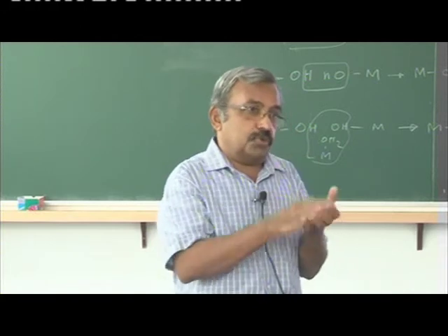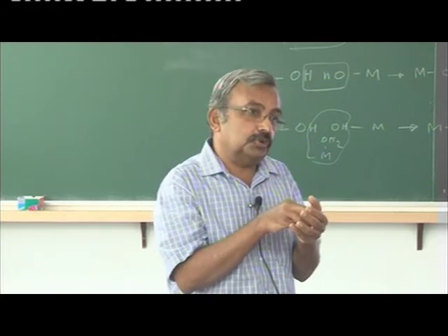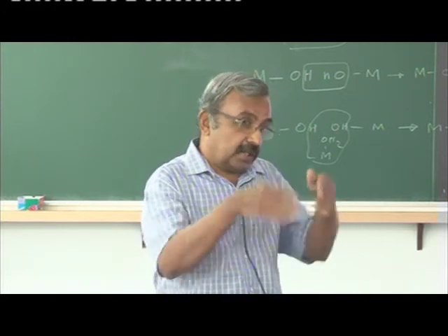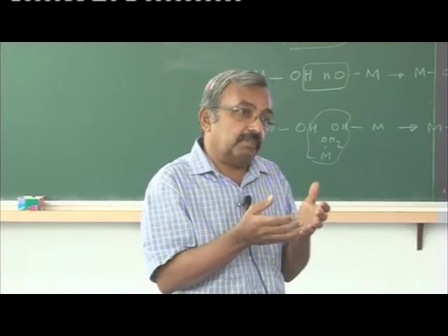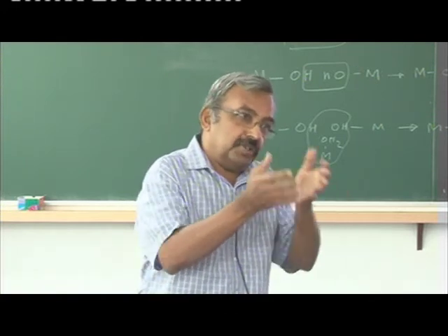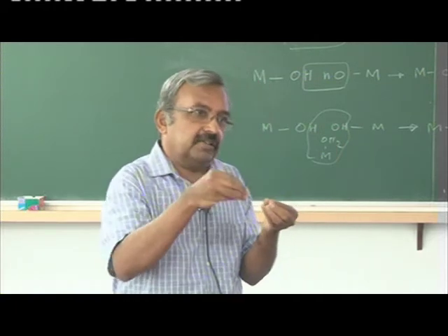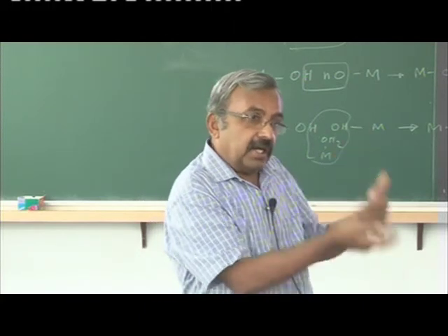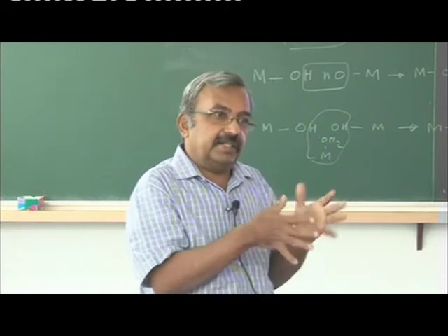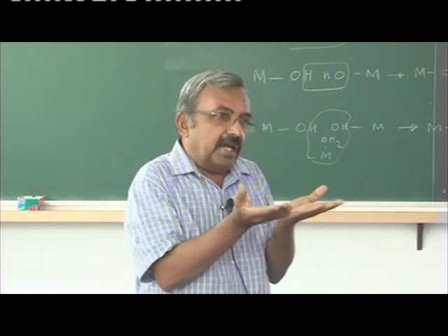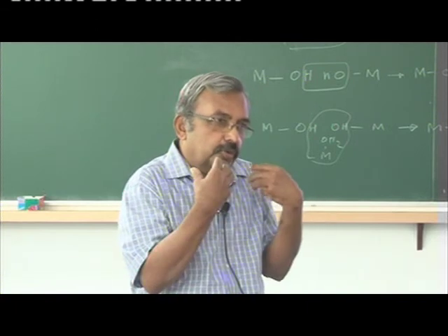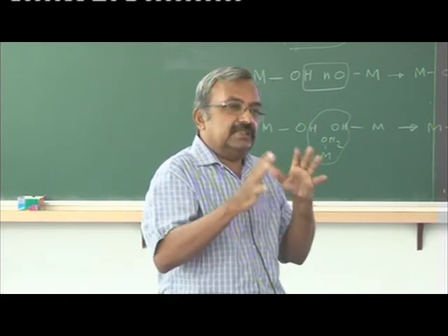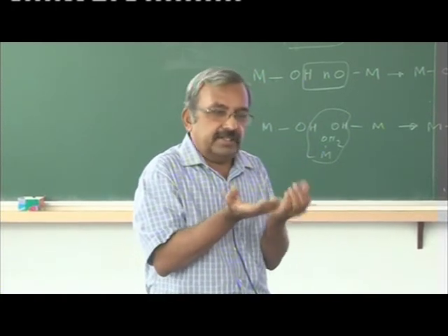Then the type of complex you use, because it balances the solubility. Meaning there are some complexes which are less soluble and will precipitate immediately. There are some complexes, basically you want the metal ion to be in the solution. That is the reason why you are adding a ligand, a complex, to keep it in the solution. Otherwise, copper will precipitate as hydroxides or oxyhydroxides, anything can happen. So to keep a balance, you want the cluster to interact with the metal complex. But this is a game which is a little difficult.